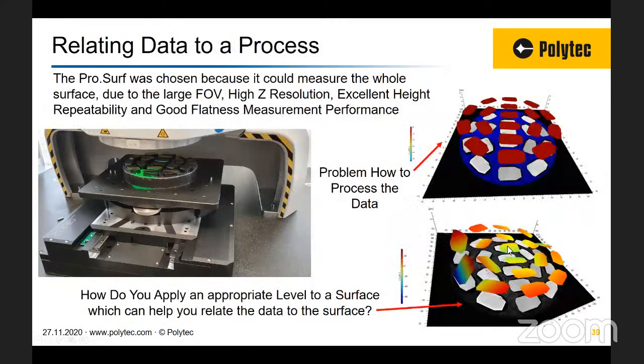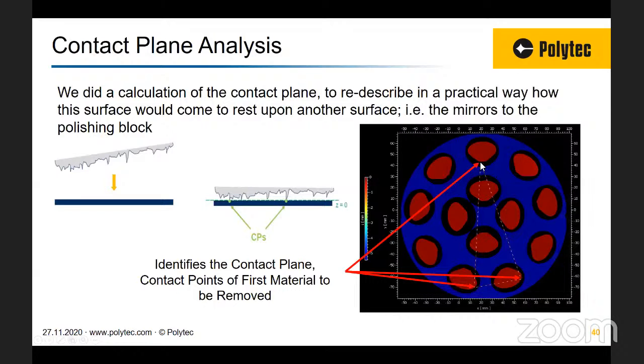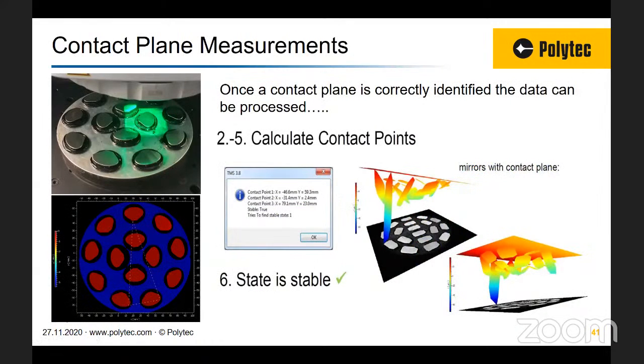If you go back here to this slide, you can see that we have a best fit plane through the data. Whereas what we needed to do was establish the contact plane. So we devised a special algorithm to analyze the whole data set and then to give us a triangulation to represent how this surface would then sit on the polishing plate. Once we've done this, of course, we could check the integrity of this contact plane. And here you can see how the contact plane would sit on the surface.